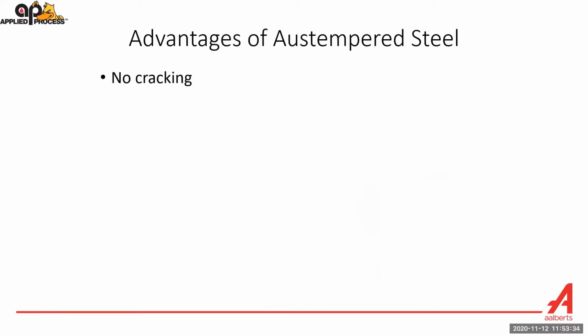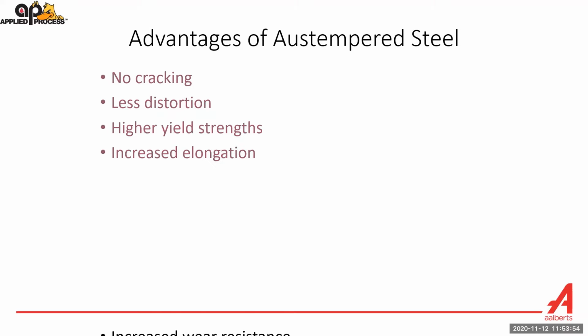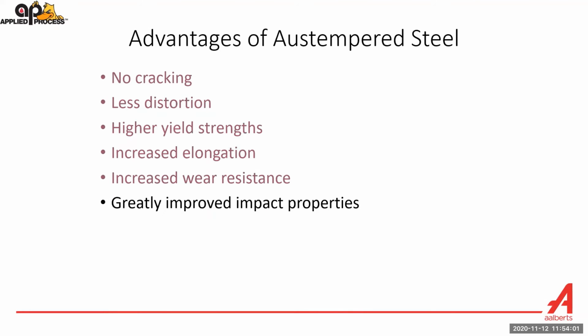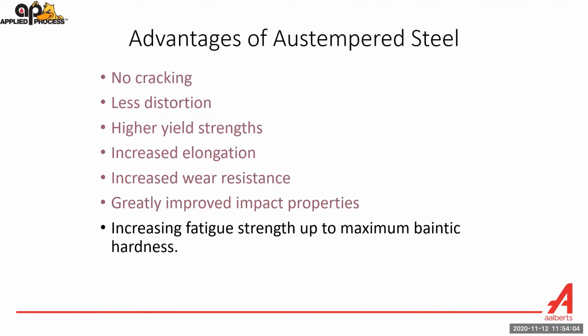So, the advantages of Austempered steel. I cannot recall an Austempered steel part that we cracked in our process. If you quench a part in oil or water, you have to come back and temper it quickly afterwards, otherwise it can crack all by itself. Less distortion, talked about that. Higher yield strength, increased elongation, increased wear resistance because the matrix is just more difficult to rip apart. Greatly improved impact properties, and increasing fatigue strength up to maximum bainite hardness.